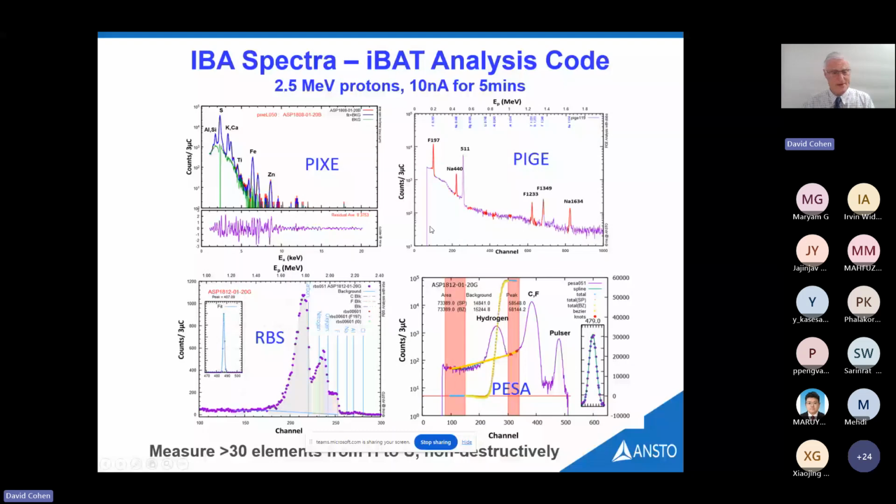Rutherford backscattering. Again, you've got your light ion coming in, hitting a heavy particle in your target. And here you get an edge, you get carbon, nitrogen, oxygen, fluorine, sodium, aluminium, chlorine. You get edges in your spectrum. And again, this is a thin sample. The area under the peak is the concentration, and the peak identification tells you what you've hit. And I've already explained the PESA, where you have a peak for hydrogen removed from all the other elements.